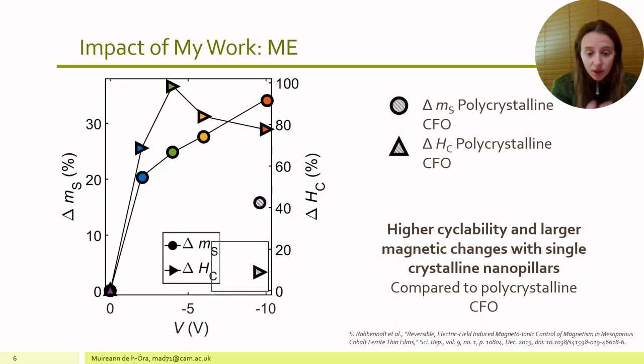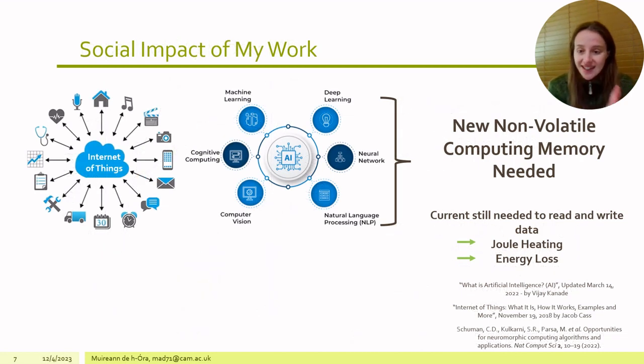If we look more closely at the magnetic properties, we can see that up to applying -10 volts, we can achieve really large changes, whereas the polycrystalline structures achieve considerably less. So we've created a model system of these single crystalline nanopillars that enhances ion migration in and out of the structure, and the durability of the single crystalline material also enhances the cyclability. So that's the scientific impact.